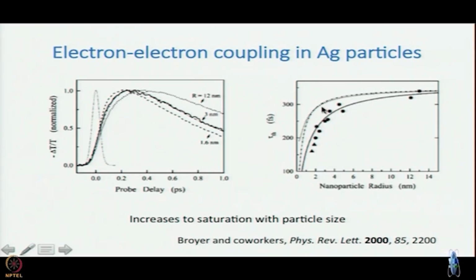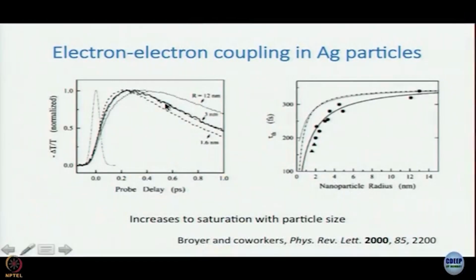Right now, do not worry about what this line is or what this curve is, just look at the points. Remember, this is silver and it increases from, actually their observation was with 2 nanometer. So, there about 150 femtosecond time constant was there and it went up to 300 femtosecond. And from the data you can see that the trend is there, it is not a fluctuation. Once again, it is impossible to get believable data. I mean, it is impossible to differentiate between 300 femtosecond and 150 femtosecond if you do not have data of this kind. I am sure this was a very, very painstaking experiment, especially 19 years ago.